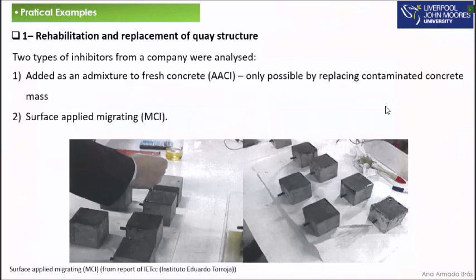So two types of corrosion inhibitors from a company were analyzed. One was added as an admixture to fresh concrete, which I will call AACI, which is only possible to use by replacing contaminated concrete mass. And then we compared that performance with the performance of a surface applied migrating inhibitor, which I call MCI.